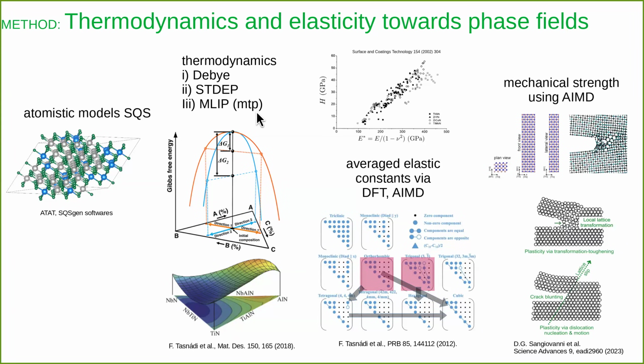Or in the case of anharmonic materials, I mentioned already the vicinity of instability. So a very anharmonic case, which occurs in nitrides, a major class of materials we are focusing on. So we use the stochastic temperature-dependent effective potential method to sample the materials at different temperatures, or in case we would like to speed up more, we develop a machine learning interatomic potential. At the moment, in most cases we are using the MTP-based setup.